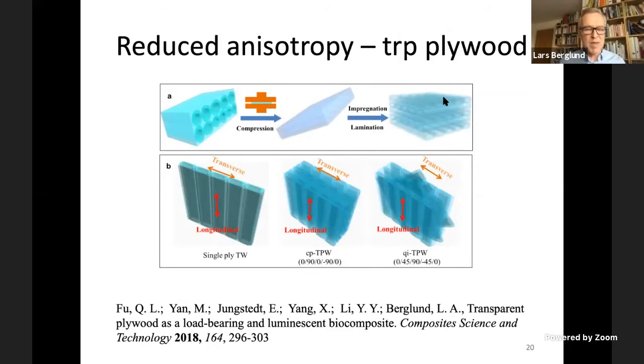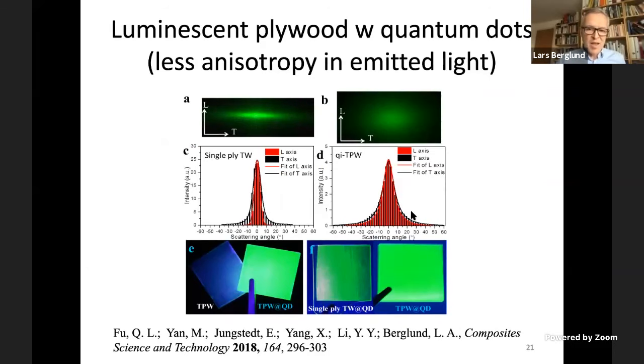So in many cases, you would like to reduce the anisotropy. And then obviously you can borrow inspiration from plywood. So you can make multi-layered materials. You can either have cross-ply laminates like this, or you can have quasi-isotropic layers in order to reduce anisotropy for the applications where you are interested in that. And then of course you go from highly anisotropic transmitted light to much more isotropic. And you see this diffused quality of light is actually something that is quite interesting in the context of indoor lighting. Diffused light is attractive. So Qi Liang here, he also included quantum dots so that he had a luminescent effect just as a demonstration. But there are many possibilities to modify these materials.